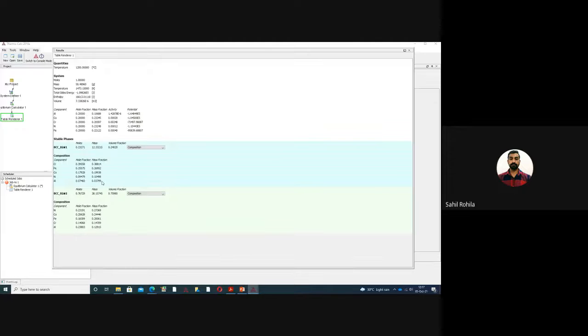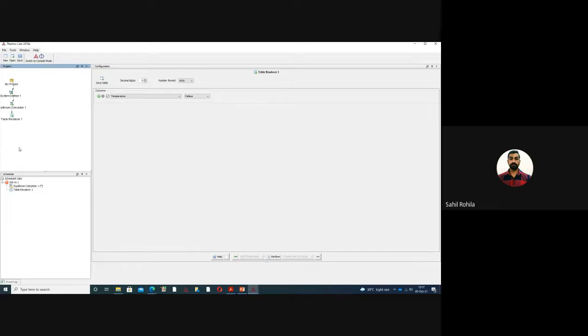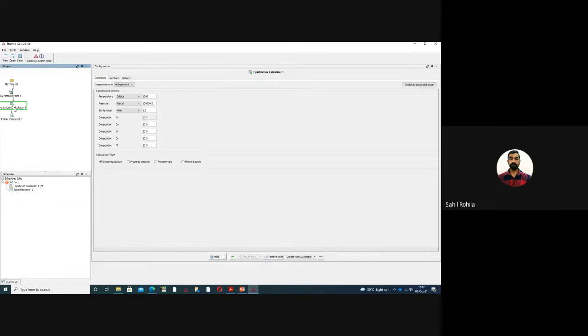So now we get to know, no, only two different BCC phases are present. One is chromium rich, another is a nickel and aluminium rich phase. Both are BCC in nature, and we can confirm through XRD and TEM that yes, they are only BCC phases. So what else can we do from this equilibrium calculator? We can calculate the solidus temperature also.